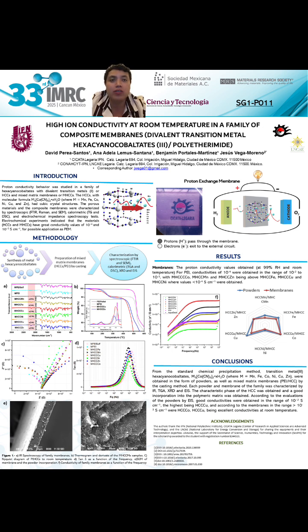As well, in the thermal analysis of the materials, we can see three losses, mainly of superficial and interstitial water molecules, as well as loss of the solvent, being stable above 300 degrees and likewise degrading at 400 degrees. Through impedance spectroscopy, we can observe different diagrams such as Nyquist, where we can see the capacitive and resistive character of the materials and the characteristic spike of the diffusion of ions in the lattice.